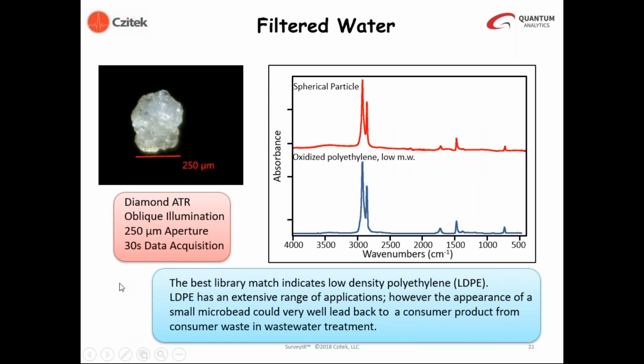Another filtered water sample, we see that this microparticle is roughly 250 micrometers in dimension. Once again, we analyzed this directly with diamond attenuated total reflection using a 30-second acquisition time. The red spectrum is the spectrum of the particle, and the primary component is polyethylene, which has likely been oxidized in the environment. In oxidized polyethylene, we see an absorption band here, which is not normally there in virgin polyethylene. That is a carboxylic acid carbonyl stretch due to incorporation of oxygen in the polyethylene chains.